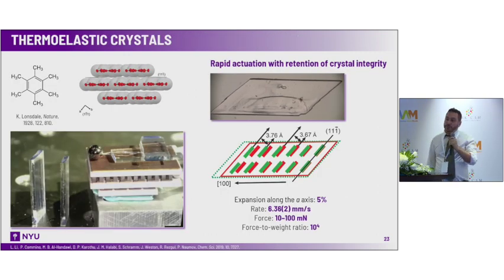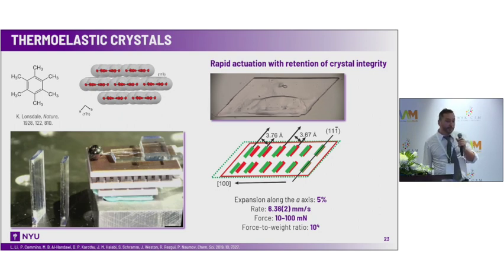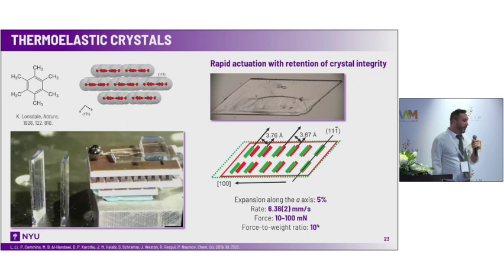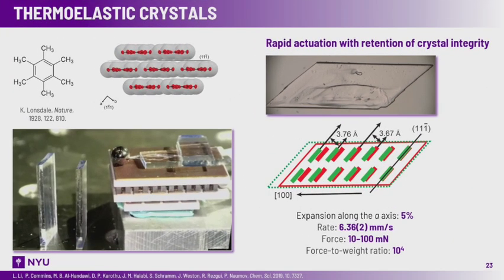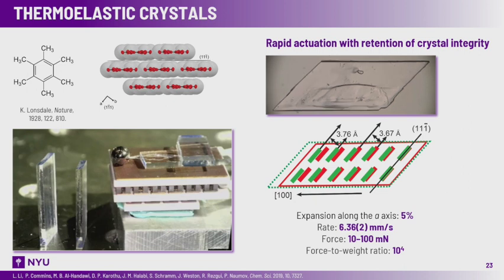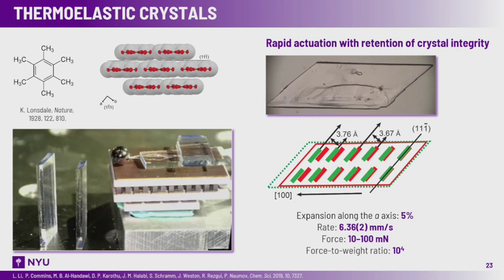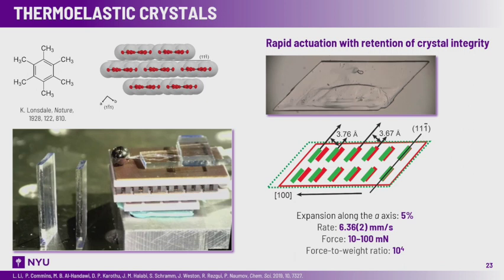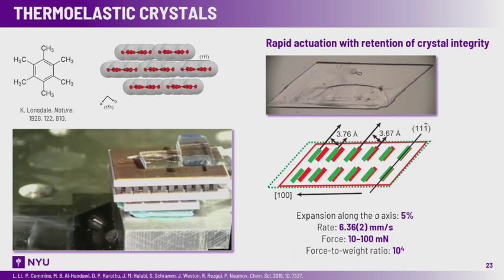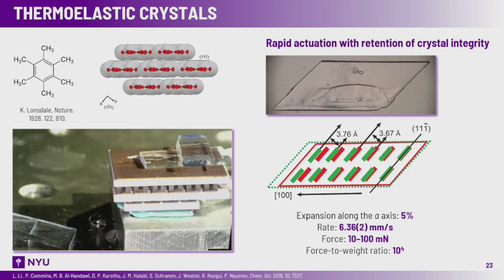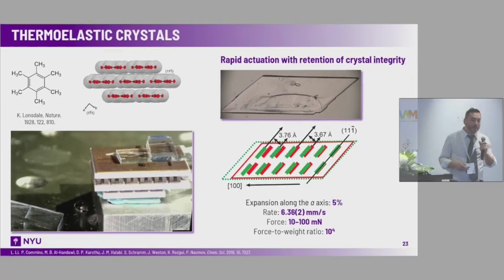And sometimes you can look at very simple compounds. Maybe some of you are familiar with this compound, hexamethylbenzene. It's a very old molecule. Kathleen Lonsdale determined the structure in 1928 to show that the benzene ring is planar and all the bonds are the same. And this is an example of a thermoelastic crystal. So it's not martensitic, but it expands significantly, and when it does that, it can perform work. We can quantify this by direct measurements of the force and compare it with other materials.